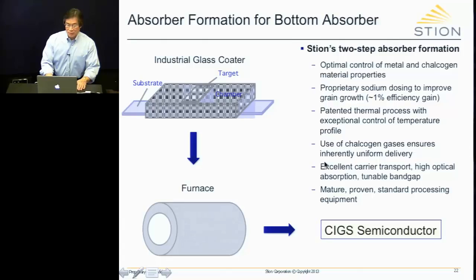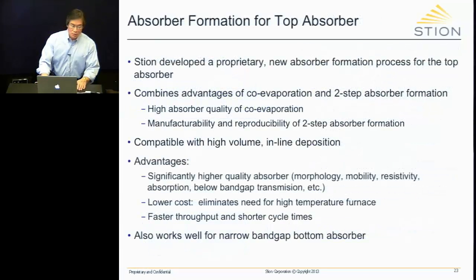But what's great about this is that the control of the stoichiometry is much better than co-evaporation. It also uses mature, proven, standard processing equipment: sputtering and furnaces. Later, I'll show you what the problem with this technique is, particularly for the top absorber. So what do we do for the top absorber?